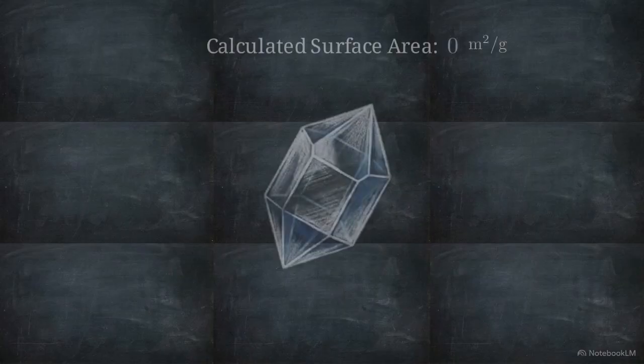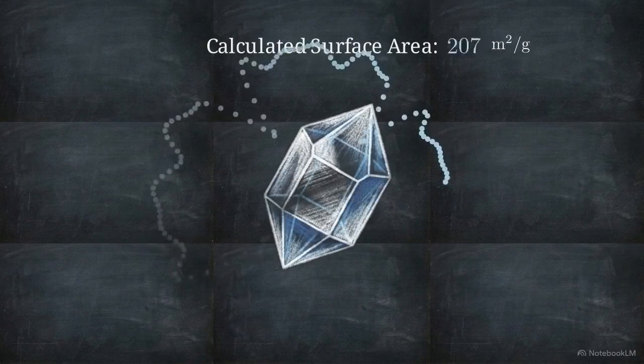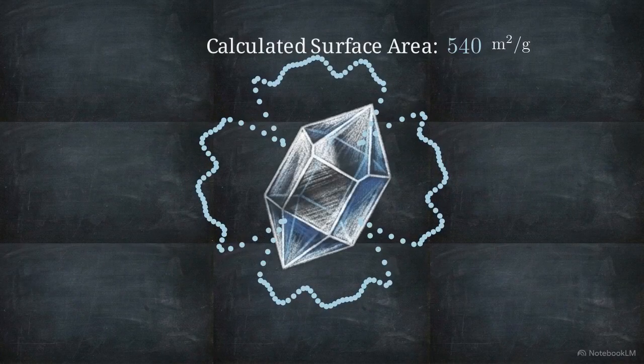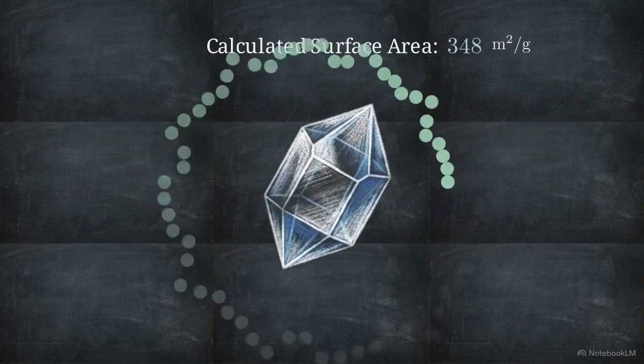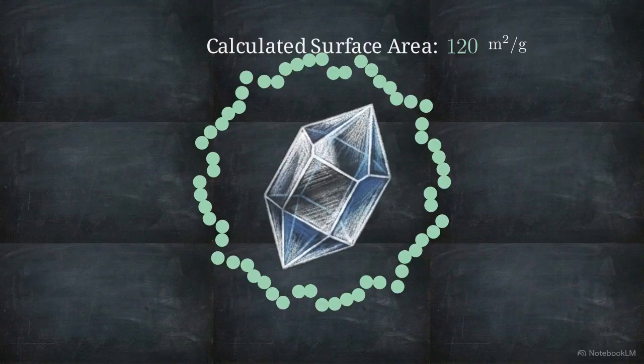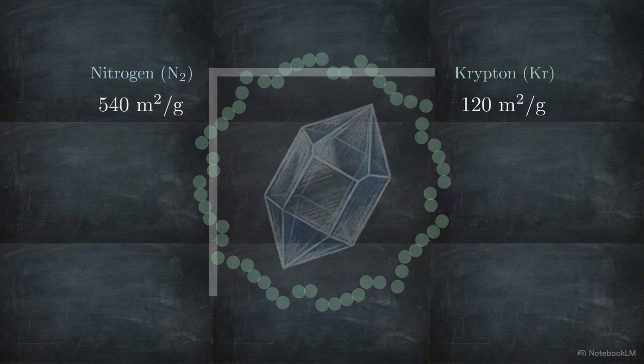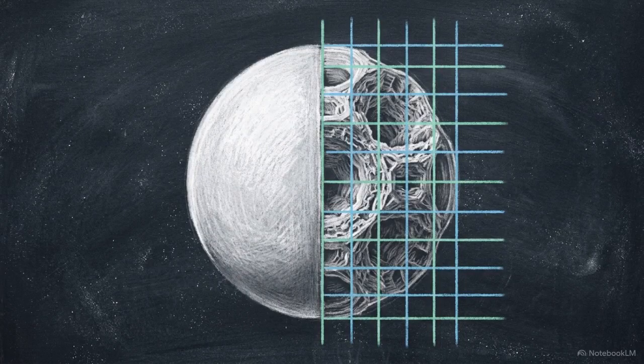The exact same logic applies to gases. If you use a small probe molecule like nitrogen, it can slip deep into tiny microscopic indentations. If you use a larger probe like krypton gas, it bridges over those micropores, resulting in a drastically different surface area calculation. In interfacial thermodynamics, the measured dimension of a surface is entirely dependent on the resolution of the molecular probe used to explore it.